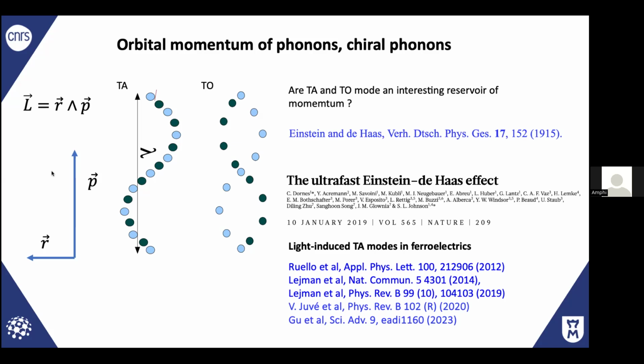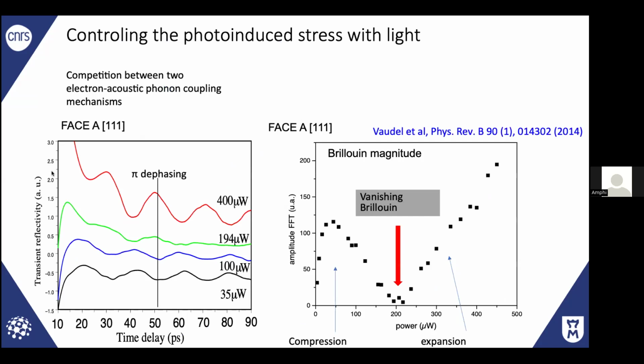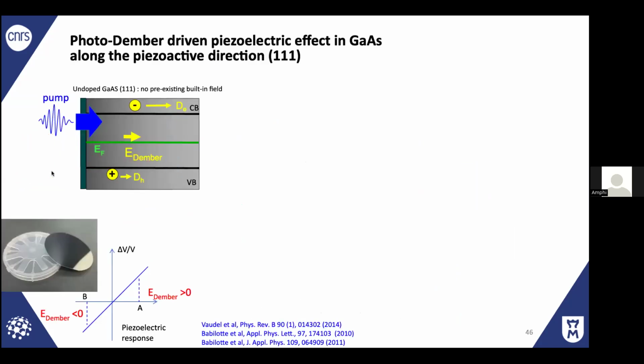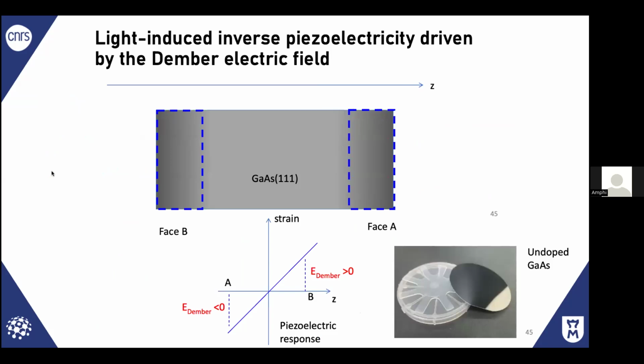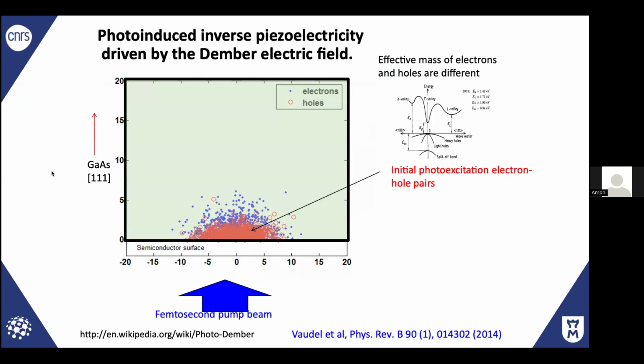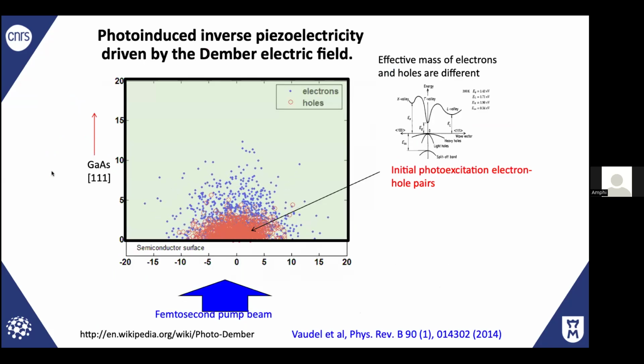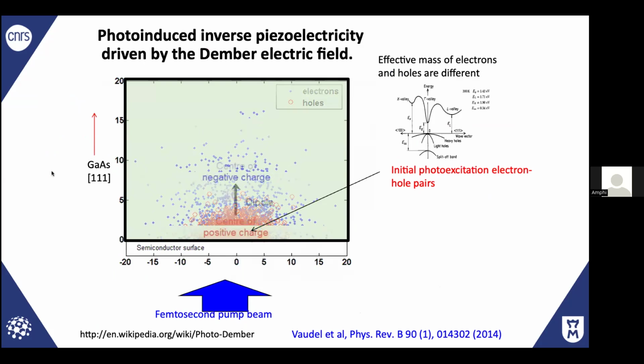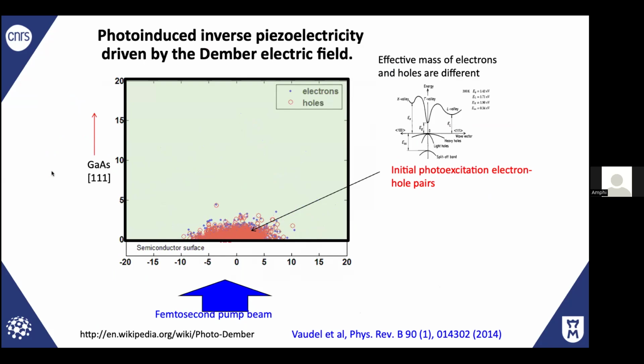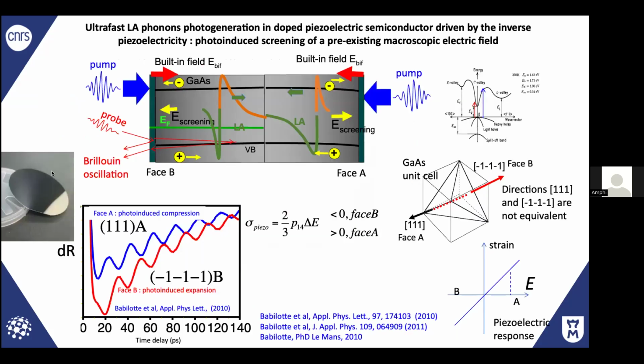And in relation to this question, in all your excitation, you don't describe the effect of the polarization of incoming light. Yes, you're right. In that case, it is not important. I would say when you have above band gap excitation, we create electron hole. The light polarization is important in the case of a birefringent material, because the light polarization can tell you that you are absorbed along either the ordinary or extraordinary axis. That can give rise to different concentration of electron hole created with light, because you do not excite the system the same way.